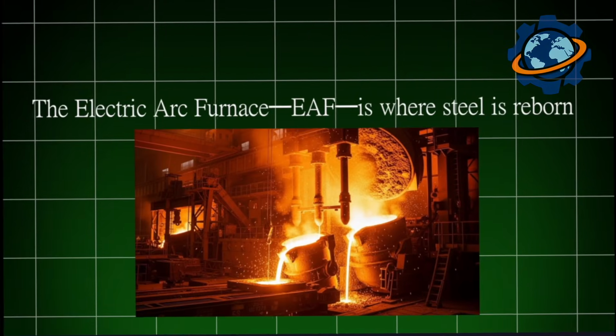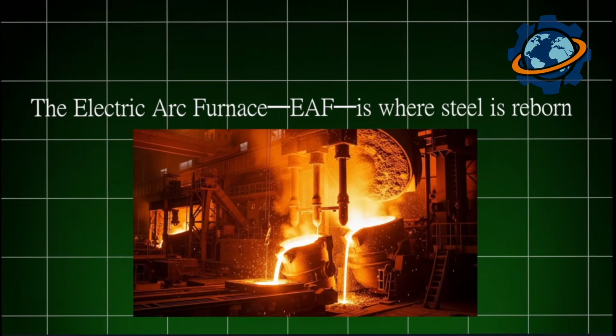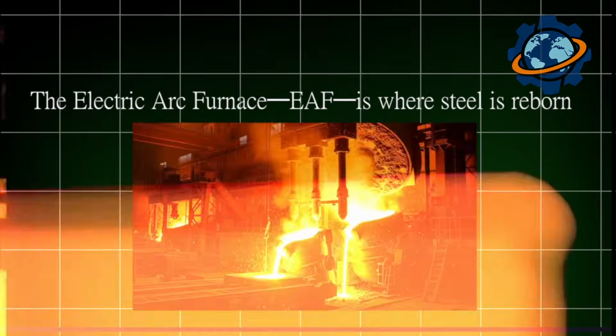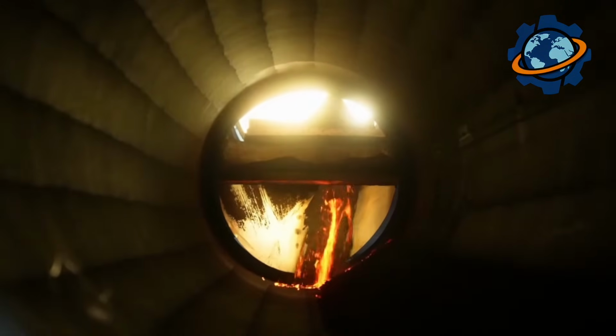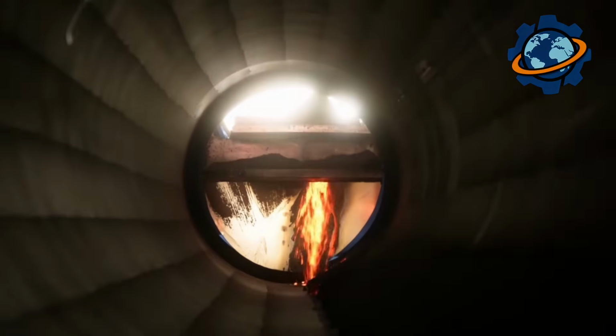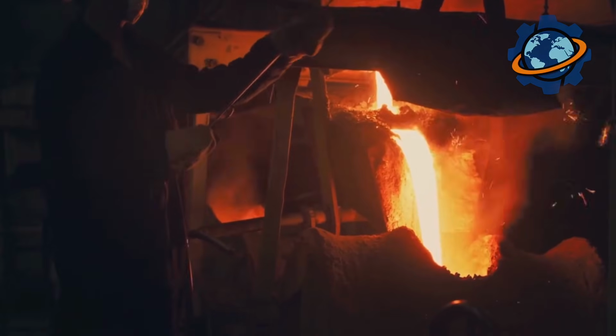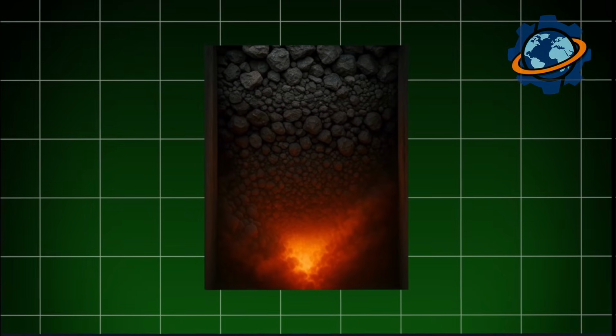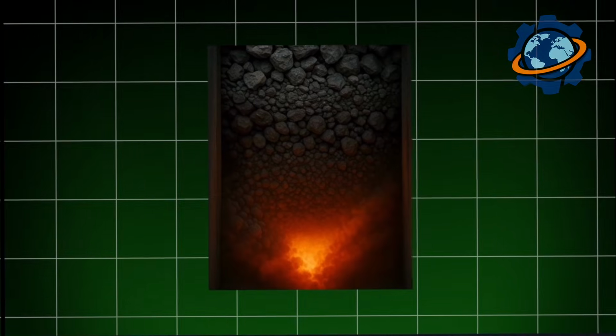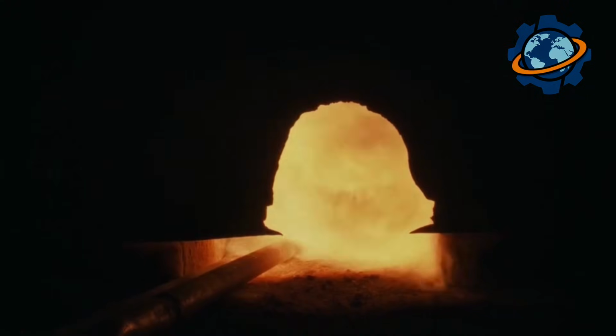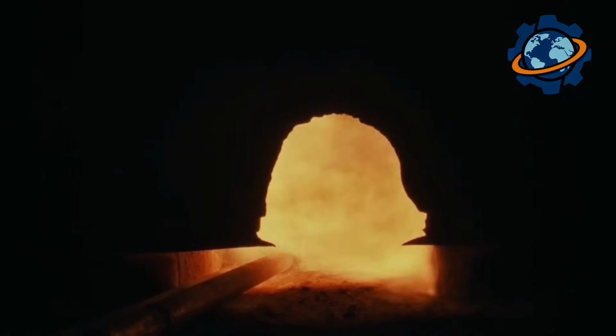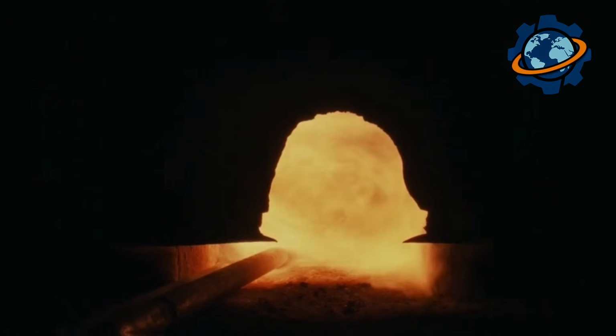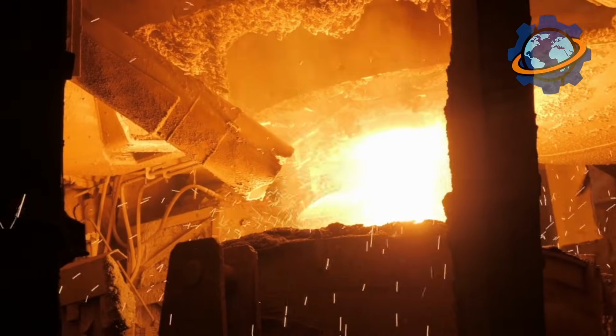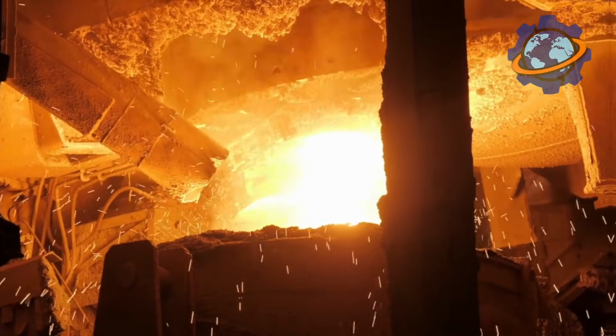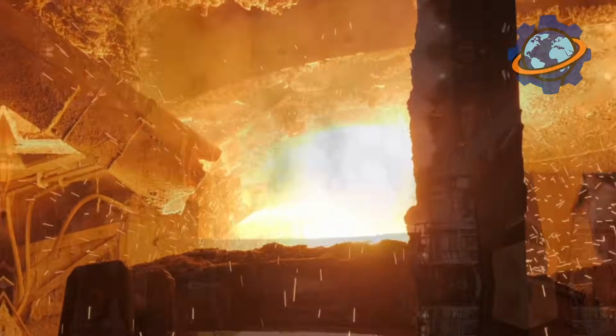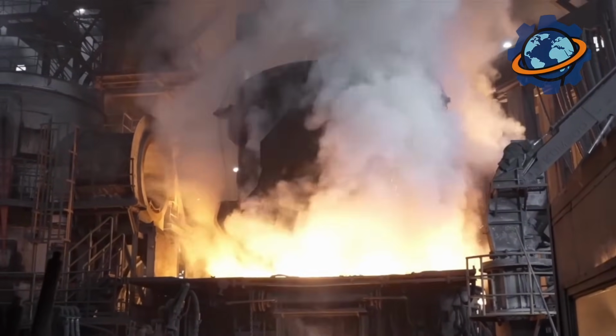The electric arc furnace, EAF, is where steel is reborn. This vessel, 40 feet diameter and 30 feet deep, operates through electrical violence. 3 graphite electrodes, each 2 feet thick and 15 feet long, descend from the roof. When power flows, 90 megawatts, enough electricity for 70,000 homes, arcs jump between electrodes and scrap, generating temperatures exceeding 5,000 degrees. The initial charge contains 200 tons of scrap steel loaded via overhead buckets.